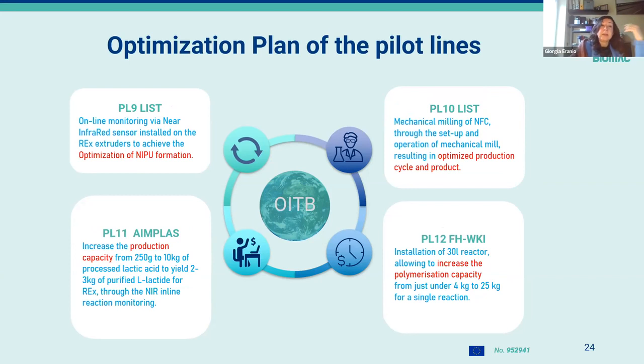Pilot line 9 put in place an online monitoring via near-infrared sensor installed on the reactor extruders to achieve the optimization of the NIPU formation. The pilot line 10, again by the same partner, put in place mechanical milling of NFC through the setup and operation of a mechanical mill, resulting in optimized production cycle and product. Pilot line 11 by AIMPLAS increased the production capacity from just 250 grams to 10 kilos of processed lactic acid to yield up to 2 or 3 kilograms of purified lactide for reactive extruders, with NIR inline reaction monitoring.